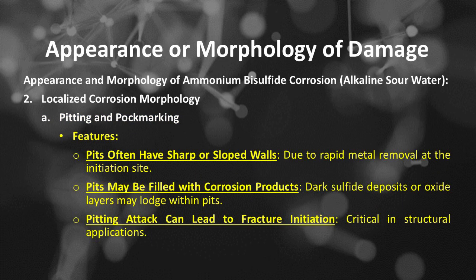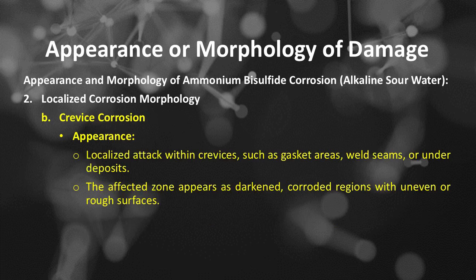The features of pitting and pockmarking include: pits often have sharp or sloped walls due to rapid metal removal at the initiation site. Pits may be filled with corrosion products. Dark sulfide deposits or oxide layers may lodge within pits. Pitting attack can lead to fracture initiation in critical and structural applications.